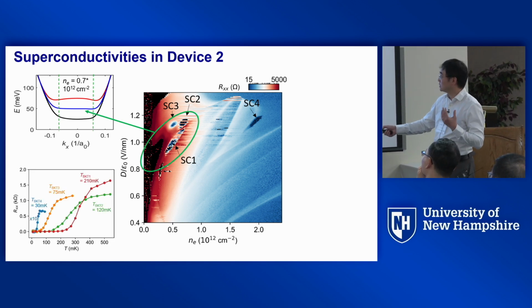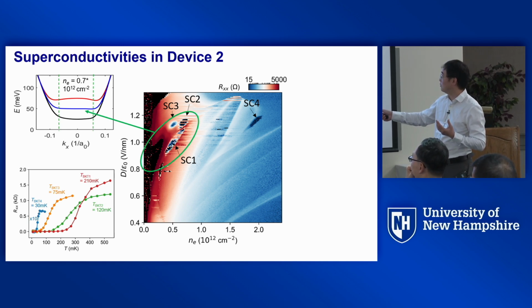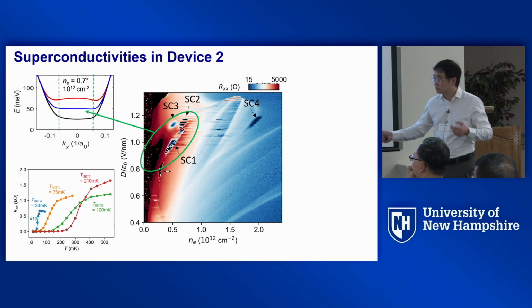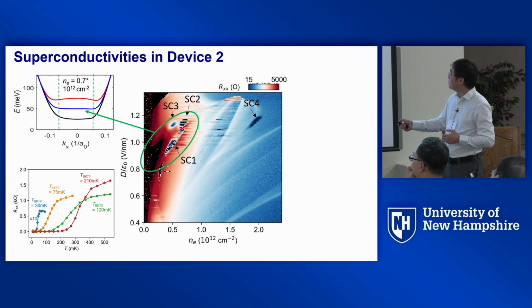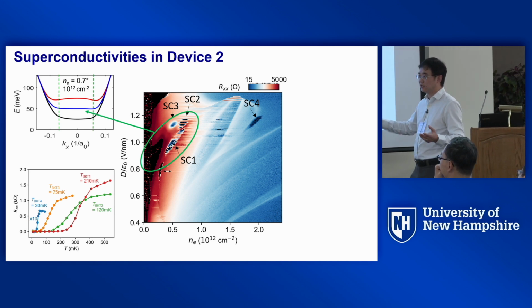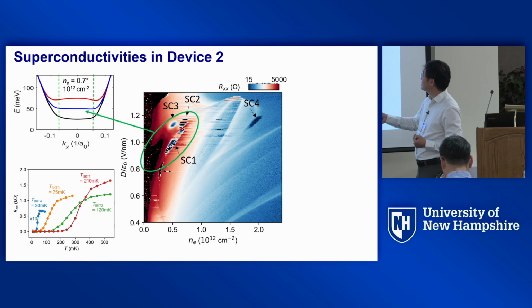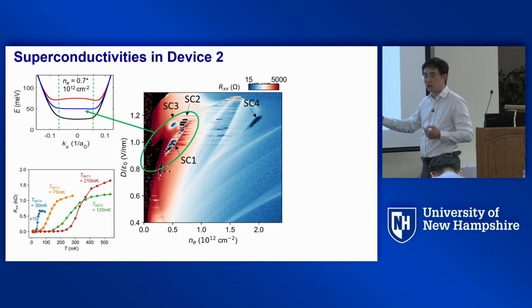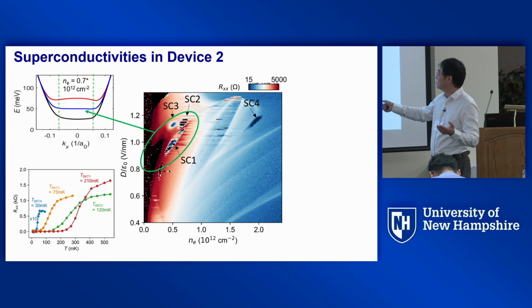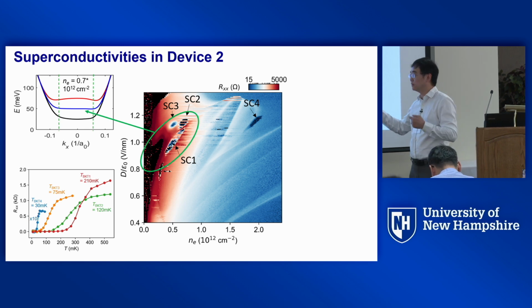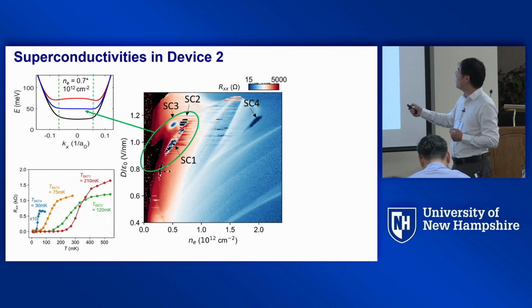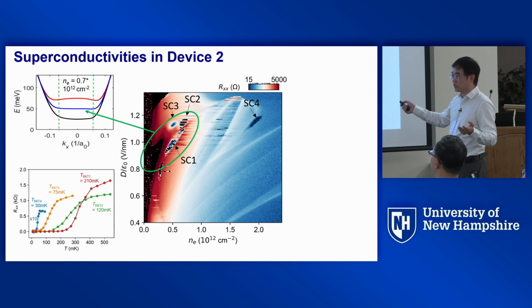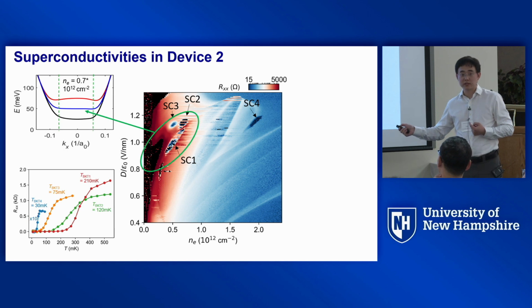As a function of temperature going down, you get different Tc. The highest one is this big oval here, roughly 210 millikelvin. And I want to point out that these 4 superconducting regions are already quite different at this level. If you see, SC1 and SC2 seem to be very fluctuating. When I told you it's an oval, well, it's roughly an oval, but there's fluctuation, kind of random jumps there. SC3 and SC4 seem to be more normal, more homogeneous. And this fluctuation is not only happening in the superconducting region, but also in the metallic region next to it. This is taken at 0 magnetic field.